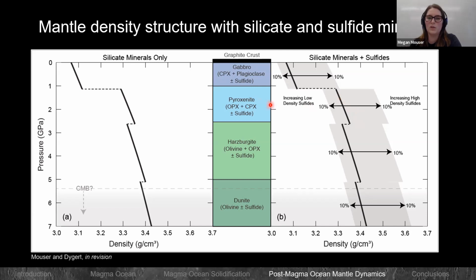If we look between the pyroxenite and the harzburgite, if you add in a significant amount of those high density sulfides, you could greatly exaggerate some of the existing density instabilities. But conversely, if you add in a fair amount of the low density sulfides, you could eliminate those instabilities altogether. So now it comes down to the question of what the sulfide precipitation would look like in Mercury's interior. We don't really know, but we can start to make some predictions with the knowledge that we do have.